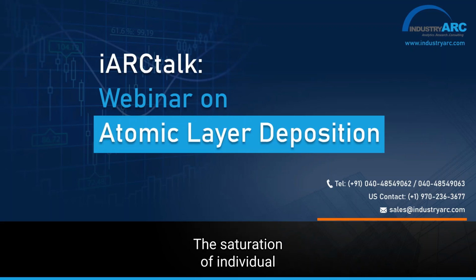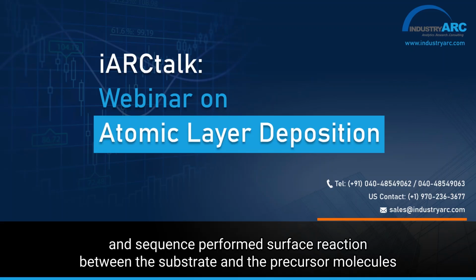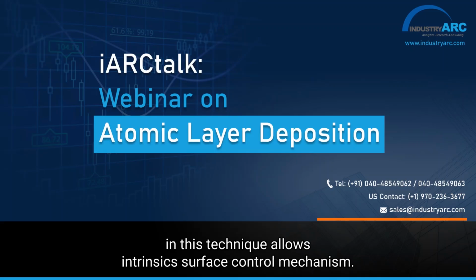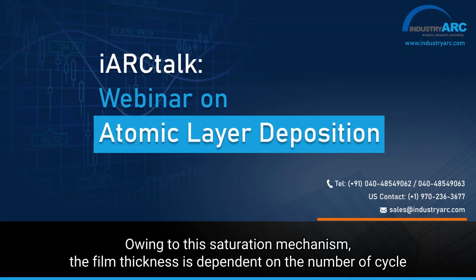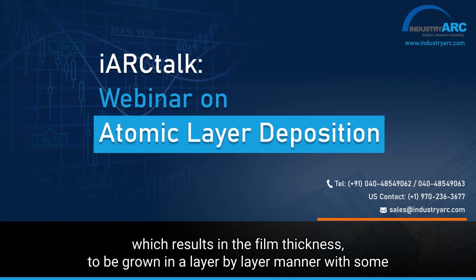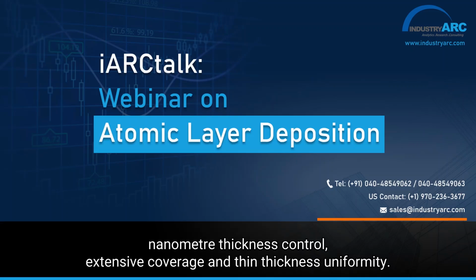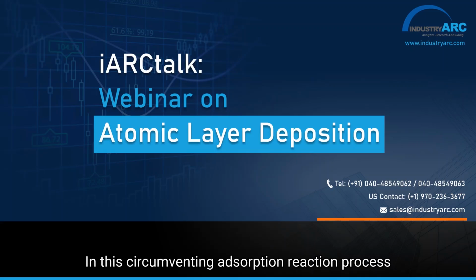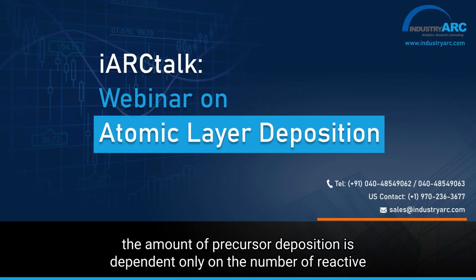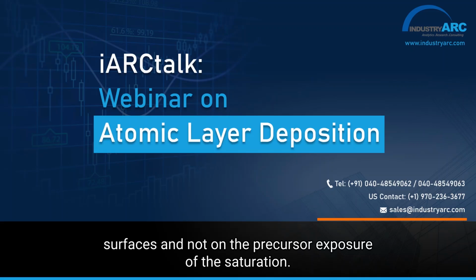The saturation of individual and sequentially performed surface reactions between the substrate and the precursor molecules in this technique allows an intrinsic surface control mechanism. Owing to this saturation mechanism, the film thickness is dependent on the number of cycles, which results in the film being grown in a layer-by-layer manner with sub-nanometer thickness control, extensive coverage, and film thickness uniformity. In this self-limiting adsorption reaction process, the amount of precursor deposition is dependent only on the number of reactive surface sites and not on the precursor exposure after saturation.